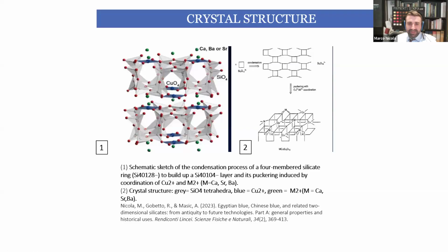So there is 1 calcium, 1 copper, 4 silicon, and 10 oxygen. And they organize themselves in a layered pattern. So you have a layered structure that is almost two-dimensional because it's corrugated. So it's not two-dimensional like graphene, but it's quite like graphite, but it's quite two-dimensional. It's almost two-dimensional.